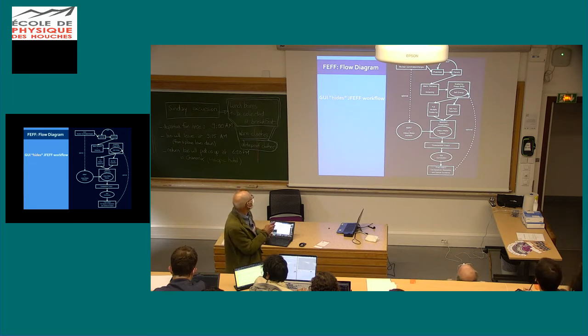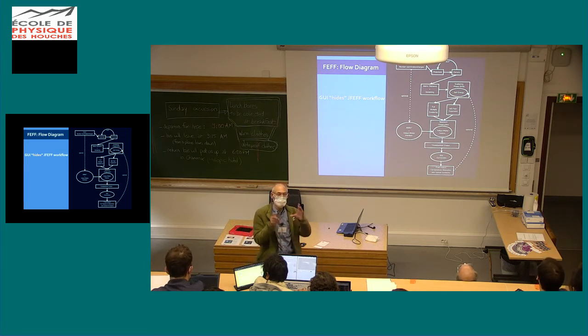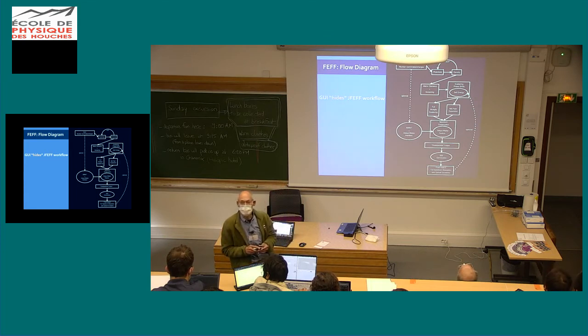As you can imagine, you take the input, create a density. We start with an overlapped atom construction of the density. We overlap them by a factor of 1.3 and get our starting point ASA, and then we do a self-consistent loop until the chemical potential is converged to millirydberg accuracy or better.